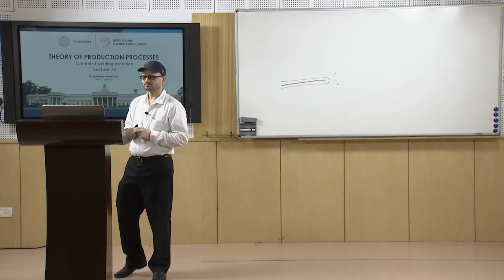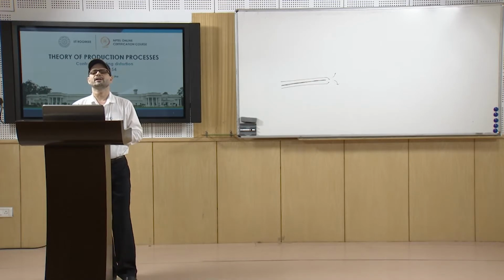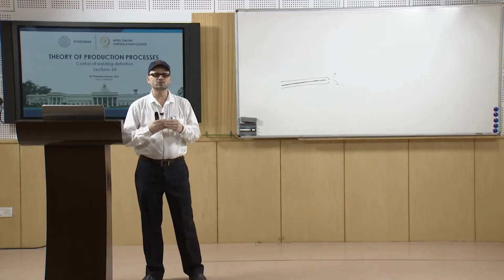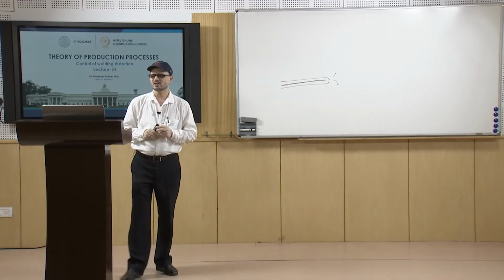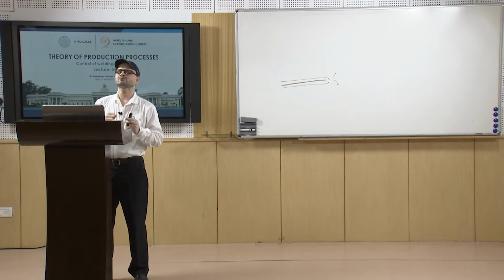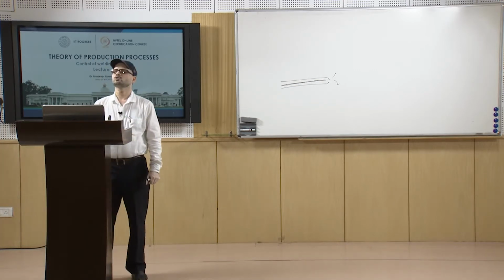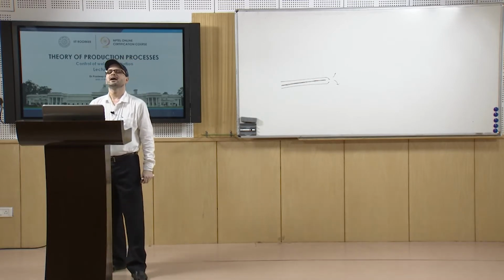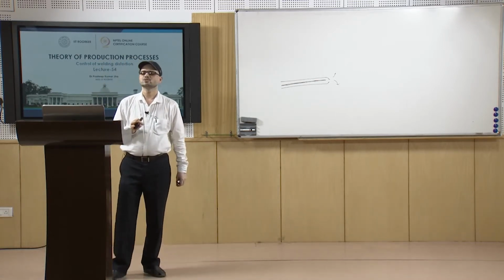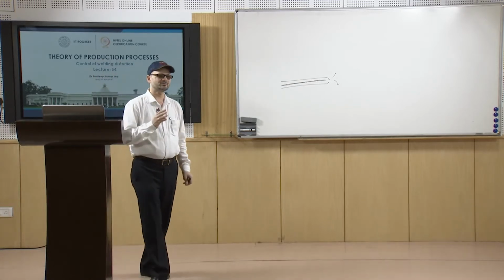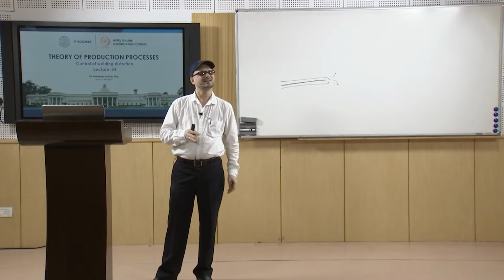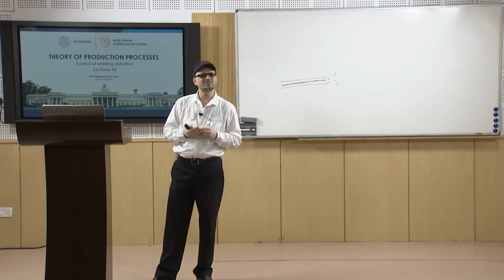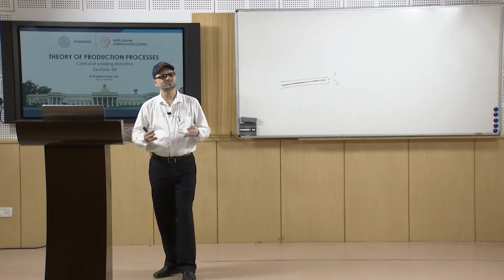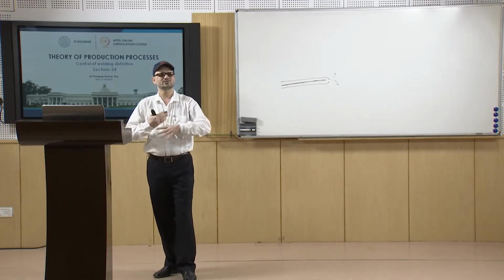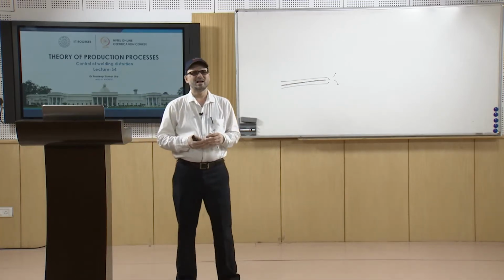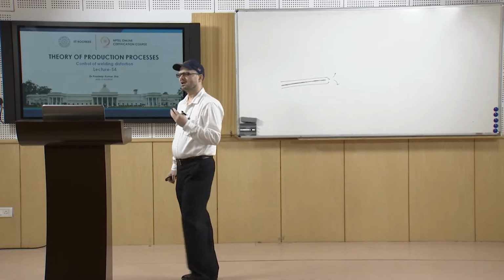Now, coming to the direction of welding. In what direction the welding should be carried out depends upon the welded structure. We have to take the precaution that it should be away from the point of restraint and towards the point of maximum freedom. That should be seen. Otherwise, if you are moving towards the point of restraint, then certainly there will be larger chances of distortion, because there will be restraint reaction stresses generated which will be larger and larger, and in that case the chances of distortion will be larger.